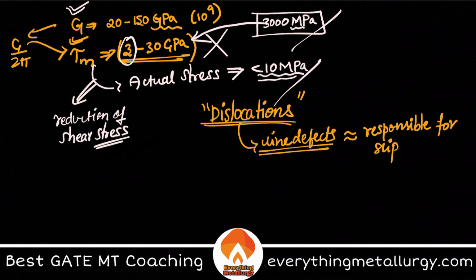We'll see in some other videos how slip takes place by dislocation movement. But you can see that from this discrepancy of values, dislocations were discovered, you can say, without looking at them. It's just a conceptual explanation of dislocation. Before even looking at dislocations, they confirmed that dislocations help the plastic flow, and that is the reason why the shear stress required is way less than the theoretical shear strength of a material, right?